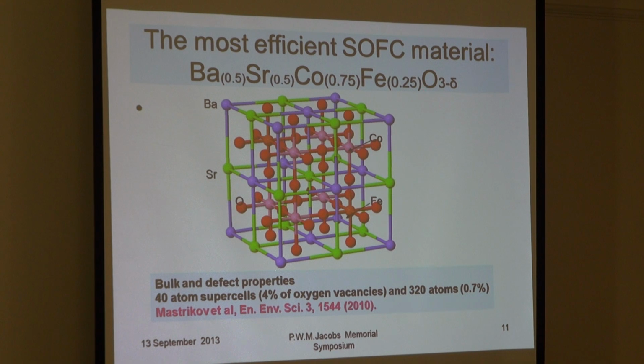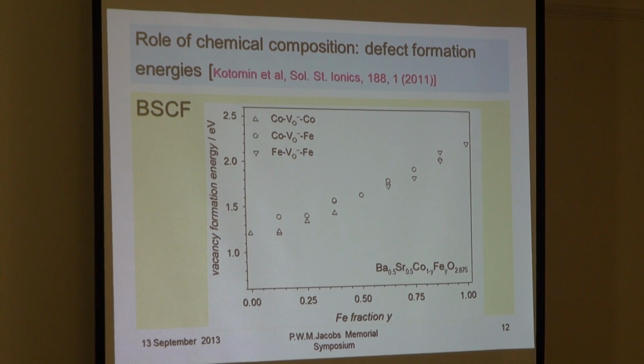And one of the reasons why it's so efficient is that it's very strongly non-stoichiometric. It means that this delta would be something like 0.7. So it's not 3, but oxygen 2.2, 2.3. So it's a huge concentration of intrinsic oxygen vacancies present in these materials, which is necessary again for very fast oxygen transfer. So essentially, we studied how properties of these materials, in particular BSCF, depend on the fraction